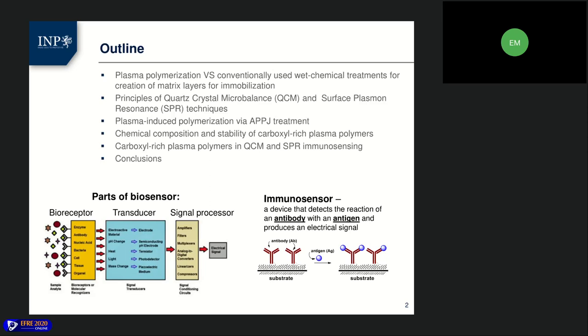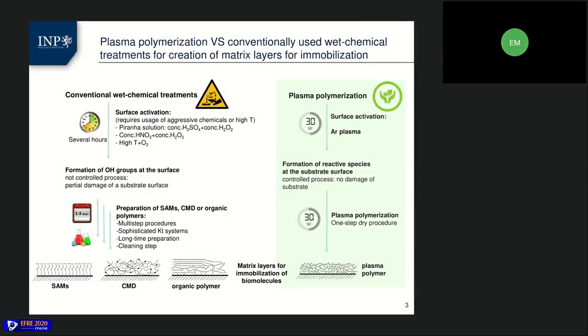As you can see, the immobilization of biorecognition elements is always required onto the sensor surface. These biorecognition elements are immobilized on a matrix layer, which is also an essential part of the biosensor. These matrix layers are typically created by wet chemical treatments, and all of them include surface activation by aggressive chemicals. The typically used surfaces are the self-assembled monolayer, organic polymers, or the most popular carboxymethylated dextran layers. The preparation of such conventionally used layers is a really long-term procedure and includes a lot of steps.